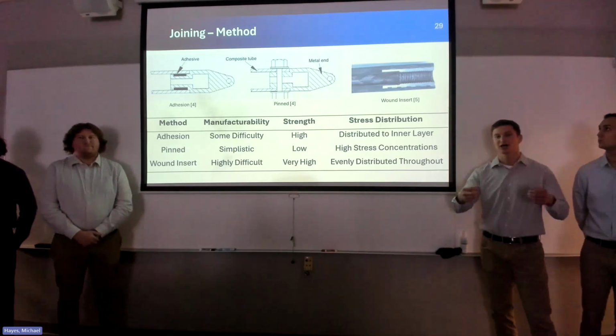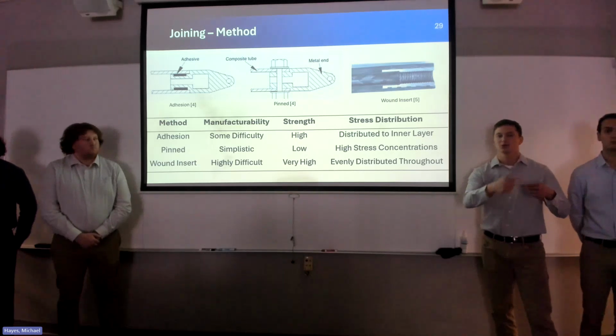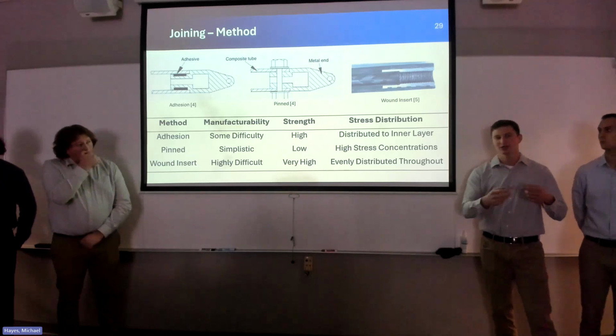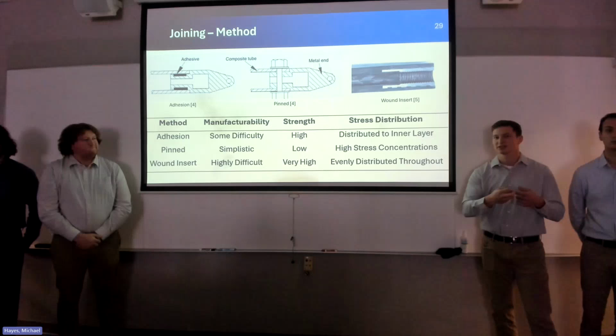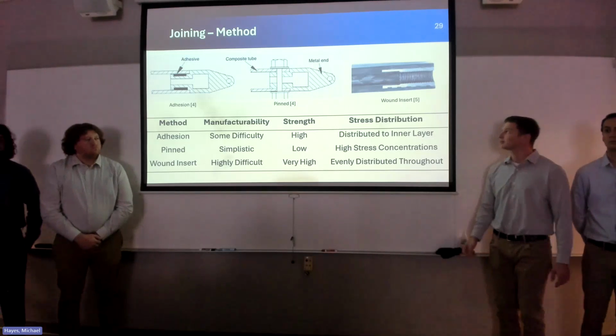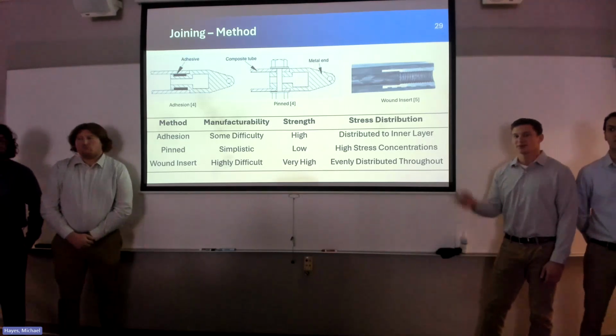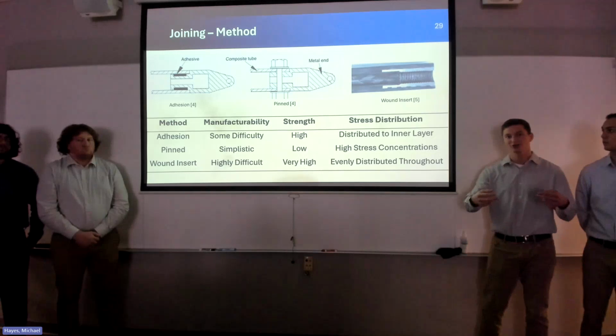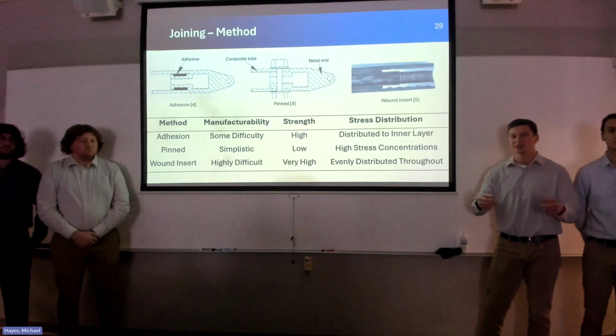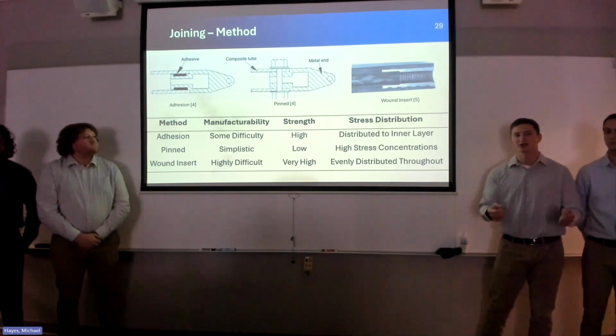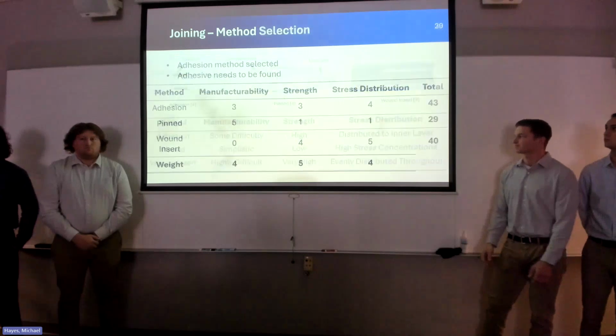You would actually put this on the mandrel when you manufacture it, and you would wind the filament around it so that you have that locking as well as that adhesion there. The only downside here is that it's very hard to manufacture. Like I said, it would be put on the mandrel, so each tube would have to be made specifically for this, and then it's hard to combine at a joint afterwards.